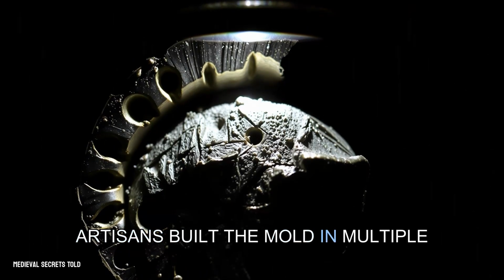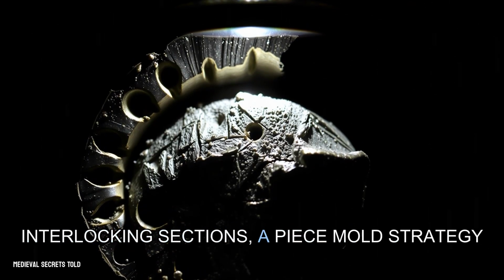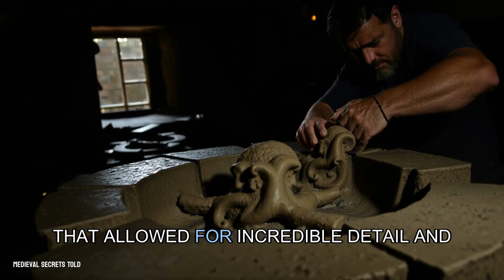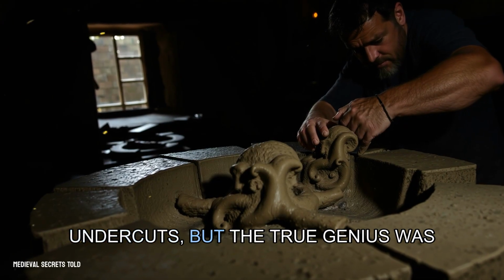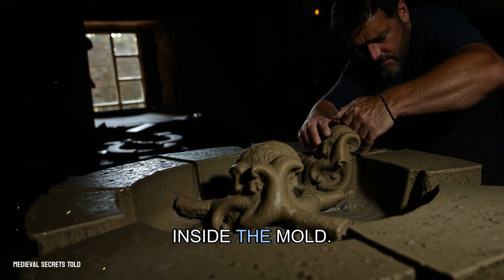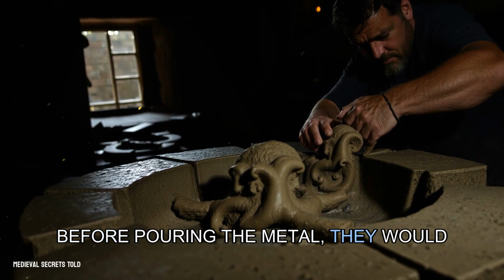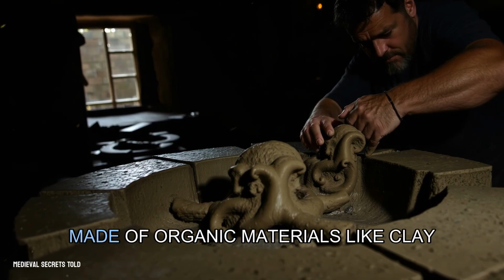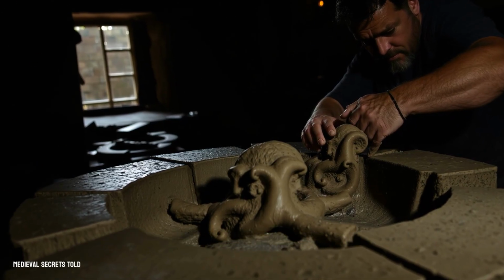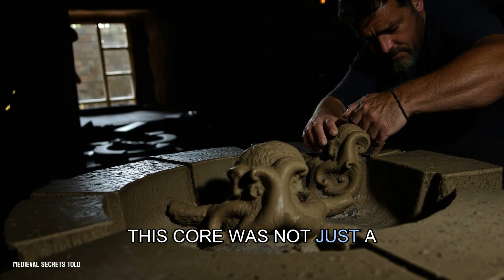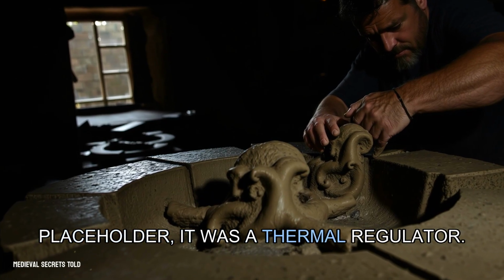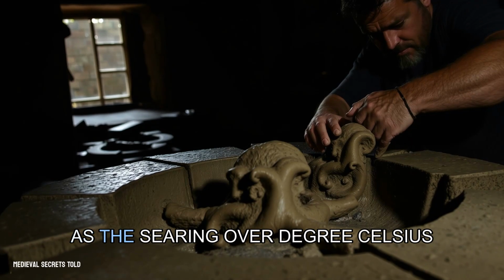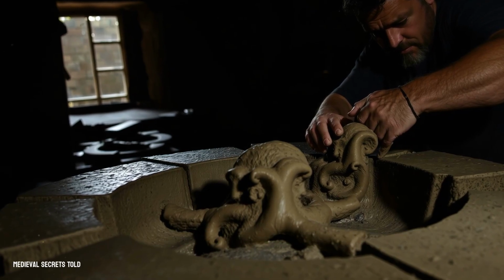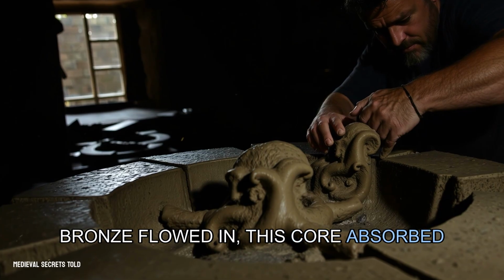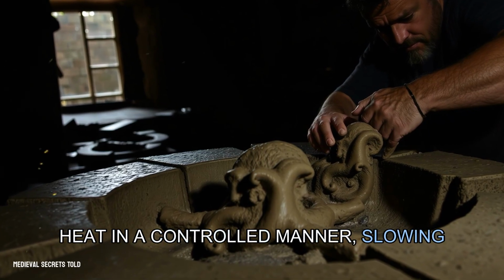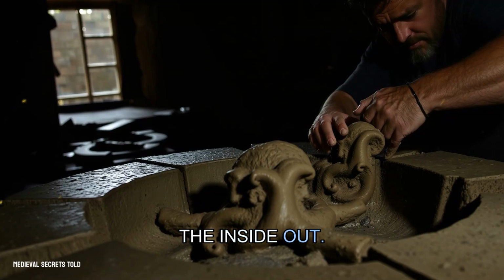Artisans built the mold in multiple interlocking sections, a piece mold strategy that allowed for incredible detail and undercuts, but the true genius was inside the mold. Before pouring the metal, they would fill the cavity with a core made of organic materials like clay and horsehair. This core was not just a placeholder, it was a thermal regulator. As the searing, over 1000 degrees Celsius bronze flowed in, this core absorbed heat in a controlled manner, slowing the cooling of the metal from the inside out.